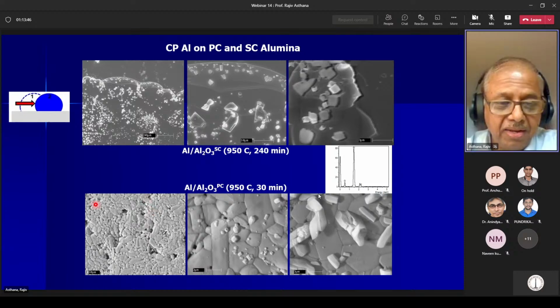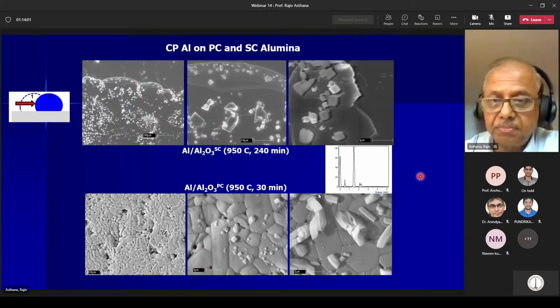So this is looking from the top after pushing the droplet away and opening up the surface underneath, and you do see these little aluminum oxide crystals that formed from dissolution and reprecipitation.